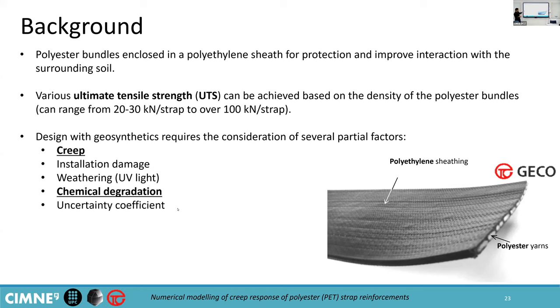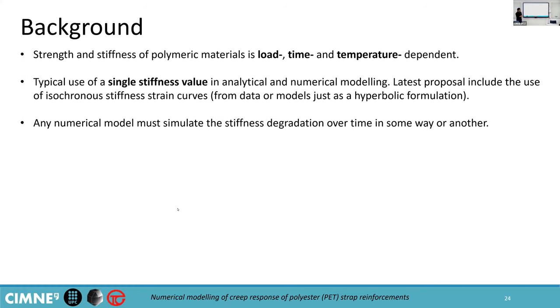For design, we consider creep, we consider installation damage, weathering due to UV light, and the chemical degradation of the fibers due to, for example, hydrolysis. Creep and chemical degradation are the partial factors of main interest for my research, and we're focused especially on creep. Geosynthetic materials are rate dependent, and polyester is no exception. This means that for different load scenarios, for different time frames, or for different temperatures, the response will vary — both the short-term response and the long-term response.